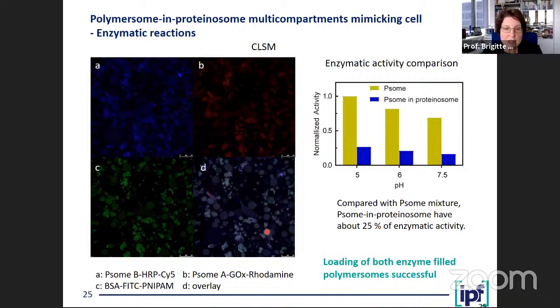And when you have the overlay, you see that really it was possible to fill the compartments with both polymersomes at the same time. And when you look here, you see that we can also see the activity of our encapsulated enzymes, which are encapsulated in the polymersome, and the polymersomes are encapsulated into the proteinosome. And you still see the activity. The activity is lower, only about 25% of the free enzyme, but it works well, and you can now have the engagement of different polymersomes within such a proteinosome.